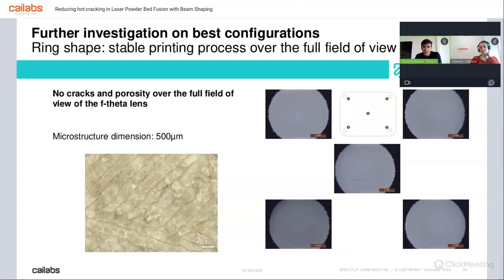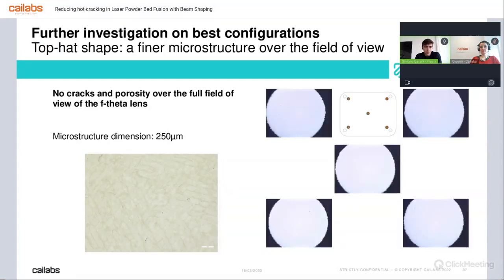As you can see in the 5 specimens that we have printed, we have no porosity and no cracks at all. Then this is just, this is not a crack. I don't know if you can see my mouse, but this is not a crack. And another important point that we have taken into account is the welding spot. Well, it's not a real welding spot because we are not welding, but the spot of the laser. For the ring shape, it was quite high, 500 microns. And this will lead us to some considerations that I will make after the presentation of the results of also